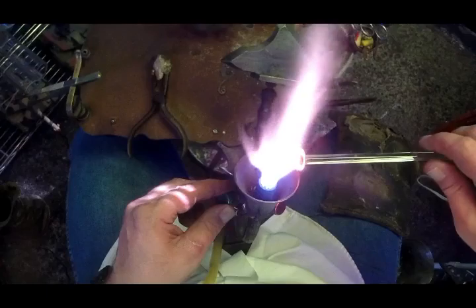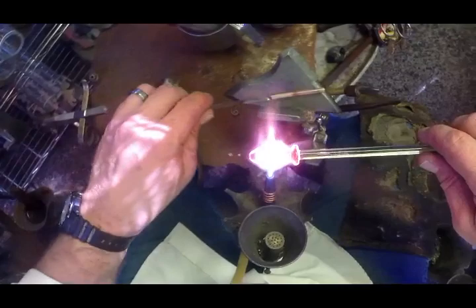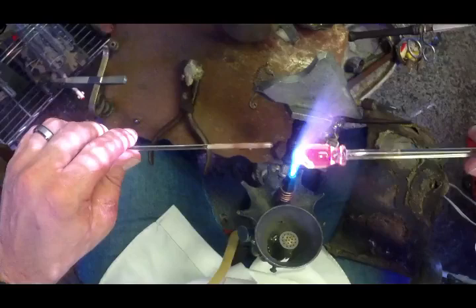Heat it up, drive the heat all the way to the core. You want the inside of this material to be molten, very glassy and extremely white hot. And then you're going to cool the outside, which is going to make a kind of a cool cylinder of fairly hot glass with molten glass inside of it. And by chilling the outside of the glass cylinder, it'll hold its shape. I don't want this thing to deform too much when I push the butterscotch into it. It's going to deform like a bullet on impact, and it's going to mushroom out.